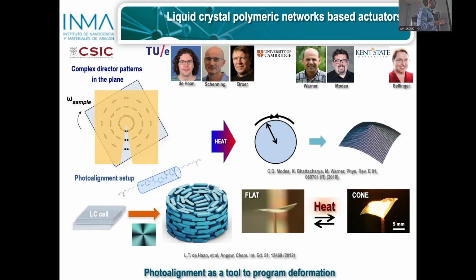So if you now take this liquid crystal cell, having two glass plates with this linear photosensitive material, you expose through this, you fill it by capillary action with the liquid crystal, and you fix this orientation, you get a texture like this that schematically looks a bit like this. And if now you heat this material, as Mark and Carl predicted, you can imagine that, remembering this deformation rule of liquid crystal elastomers, the system will try to contract around a circle and will try to expand along the radius. But we learned in school that this is not possible.